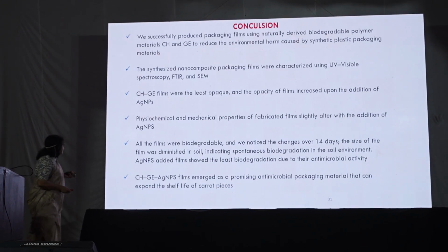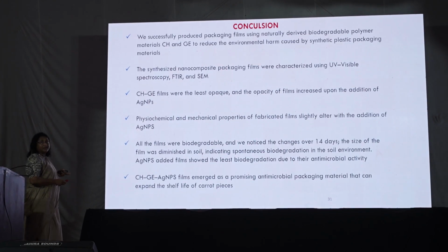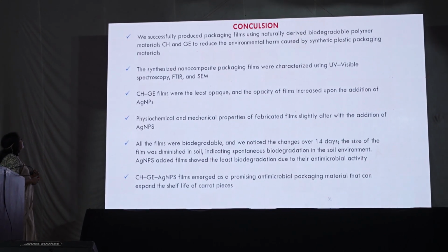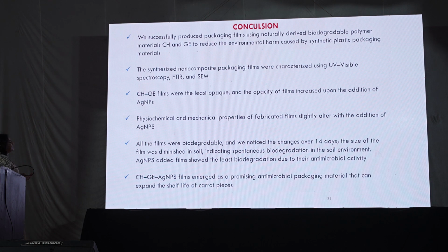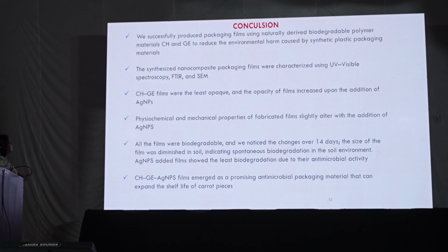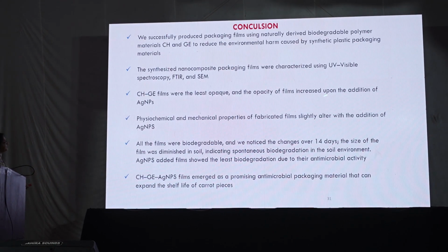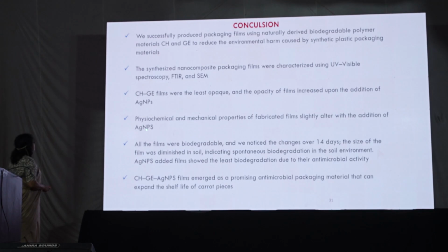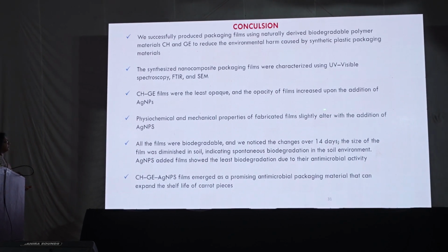And here we have successfully produced packaging films from naturally derived biodegradable polymer materials, chitosan and gelatin. The synthesized nanocomposite films were characterized and used for food packaging applications. The chitosan gelatin films were least opaque, and the opacity of the films increased upon addition of silver nanoparticles. The physicochemical and mechanical properties of the fabricated films are slightly altered with the addition of silver nanoparticles. The main interesting factor is that all the films are biodegradable. We did soil testing, indicating spontaneous biodegradation under soil environment.